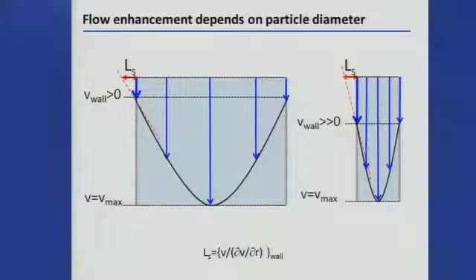When you have a small porosity, a small interstitial volume, the velocity through the material is higher. So you actually need to work at a slower volume flow rate with materials that have lower porosity. And so you actually gain two ways. One is with the slip flow, and then the other is with the smaller optimal volume flow rate. And so it makes all of these things feasible. And so we're starting to use HPLC with these really tiny little particles. I wanted to explain why it's a nanoscale phenomenon.